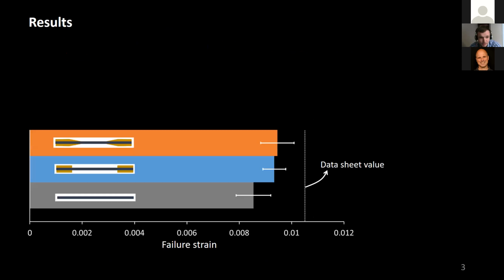So if we first look at the first 3 types of specimens, we are plotting the results here in terms of failure strain, which has to do with the continuous end tabs where we cannot measure strength directly. So if you look at the failure strain and you compare it to the datasheet value that I mentioned, then you actually see that for the pure UD, where you do not have any end tabs, if you would rely on this value, it would be a significant underestimation. But also if you do add end tabs, either with the straight edge or the chamfered tabs, you would still be underestimating the datasheet value.